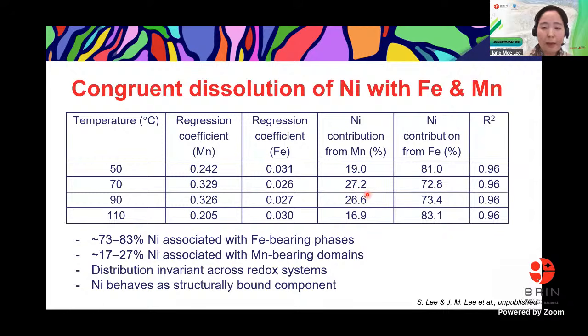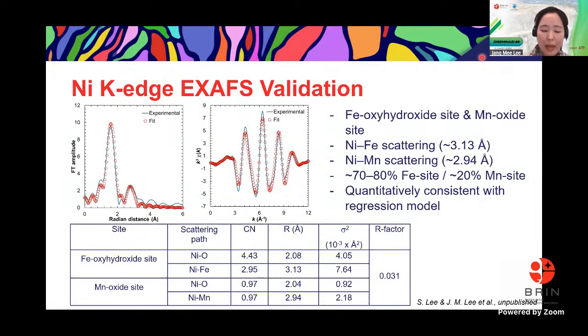So this occurs at all temperatures, and regardless of the reductant used, we found nickel is distributed in this way between the manganese phase and the iron phase. And to validate this regression-derived host phase distribution of nickel between the iron phase and manganese phase, we performed the nickel K-edge EXAFS validation.